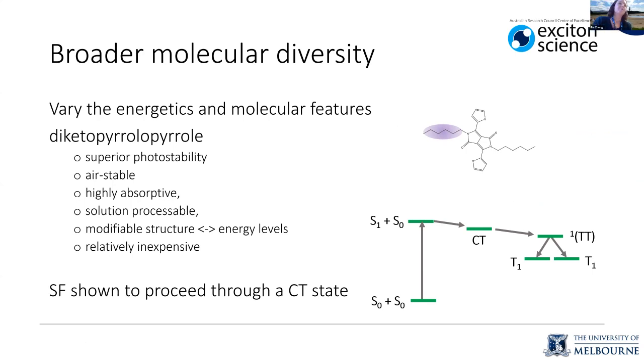And so one such more alternative chromophore is diketopyrrolopyrrole. And it has some very desirable characteristics like being photostable, which you can imagine in a solar energy conversion process is pretty important. It's air stable, it's highly absorptive, has a high quantum yield, it's solution processable, and you can modify the energetic structure through these groups on the molecule that can extend the conjugation. And then also you can change the solubility by changing these solubilizing groups here on the nitrogen. So yeah, it's pretty attractive as a chromophore.